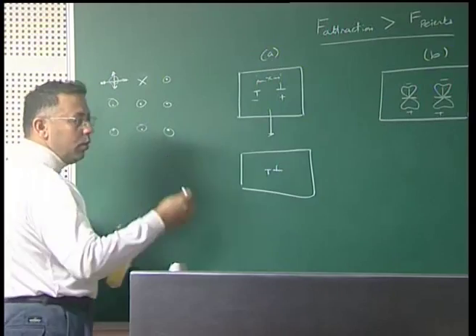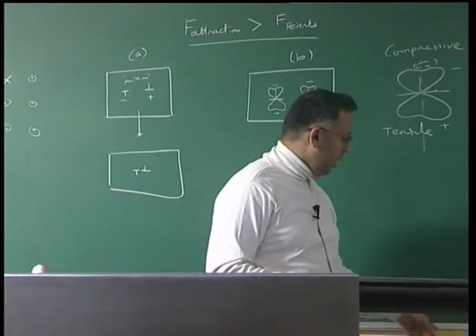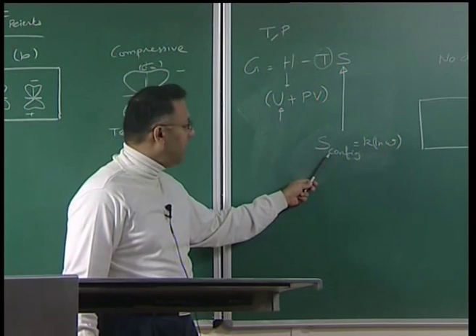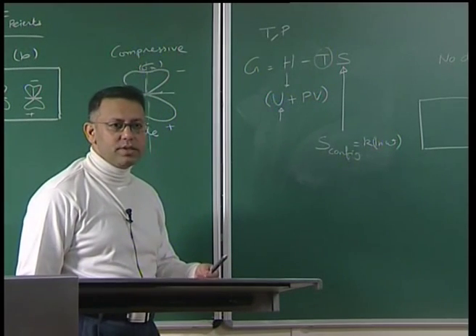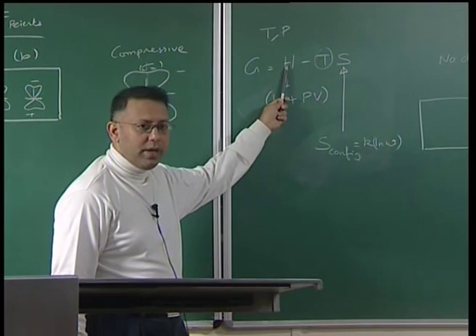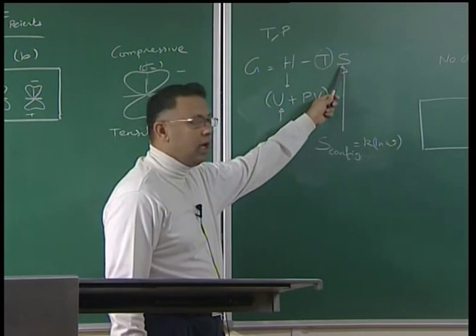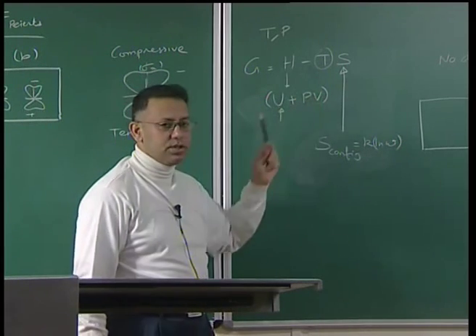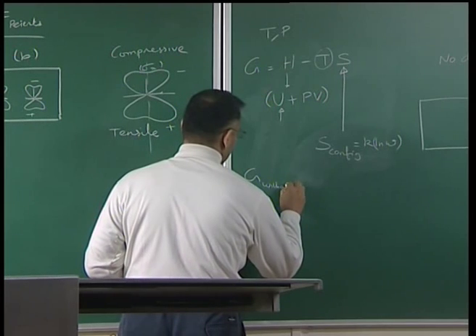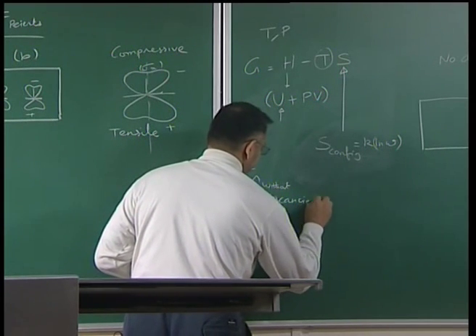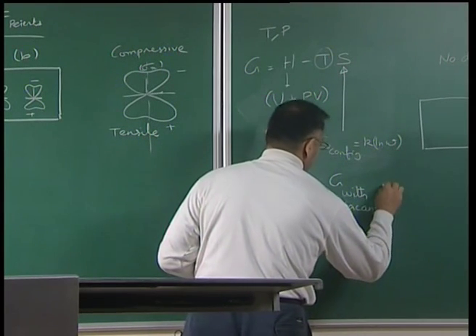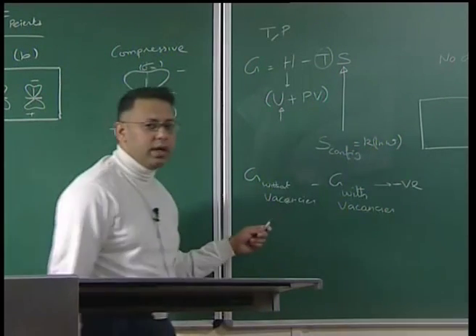A vacancy could be present here, here, or in one of many possible lattice positions, which increases the configurational richness of the system and provides an entropy benefit. Therefore, a system with a vacancy has higher entropy compared to a system without a vacancy. When more vacancies are added, the internal energy increases, but there is a certain number of vacancies that are thermodynamically stable — a number that gives the maximum entropy benefit such that the H - TS term turns negative.